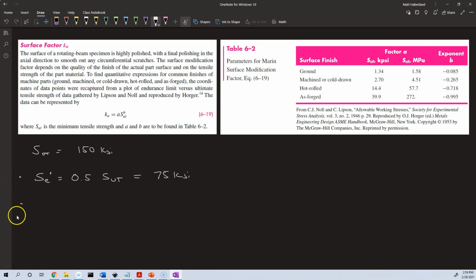And the second part was, what if it were machined but not polished? So we wanted to find out the endurance strength of our real part, which is really just a test specimen, but it's not polished, when we modify it by the surface factor Ka. And all these other factors that we could have, Kb, etc., are all 1, because we have all the other conditions of a specimen except for the surface finish, times Se prime. And Ka is given by this equation here. Ka is equal to a times ultimate tensile strength to the bth power, where a and b are given in this table. And we have a machined part, machined or cold drawn.